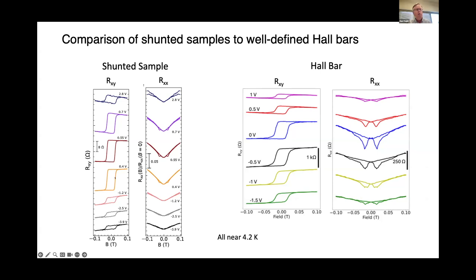But already in those devices, we were seeing kind of nice phenomenology. If you look at the Hall resistance as a function of magnetic field, we saw nice square hysteresis loops with good coercivity near zero field. The magnitude of the Hall signal was quite strongly peaked near the Dirac peak as we gated the devices. The different curves correspond to different gate voltages. And by looking at the background slopes, we could tell where the Dirac peak was. The slope of the ordinary Hall effect changed as we swept through where we're seeing large signals. But still, the resistance changes were on the order of 10 ohms or so, not huge.